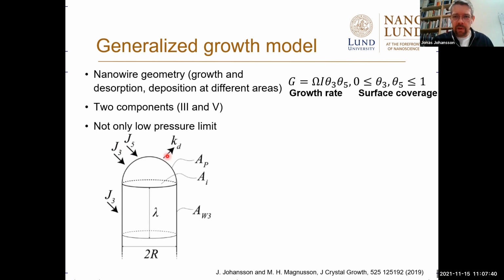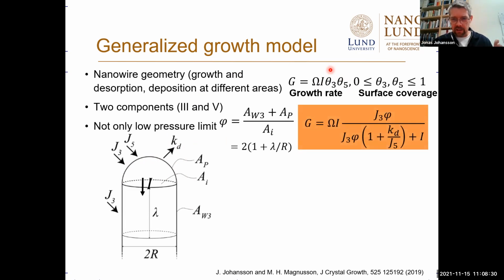So the growth rate is a maximum growth rate or a growth rate coefficient, like a chemisorption incorporation rate if you want, and the molecular volume of a 3-5 pair, just to get the units right, and then the surface coverages of the group 3 and the group 5 here around the growth interface, and it's these that are being modeled and plugged into this growth rate. And I don't have time to talk much in detail about the modeling. I will not set up the equations, but I will show you the results here.